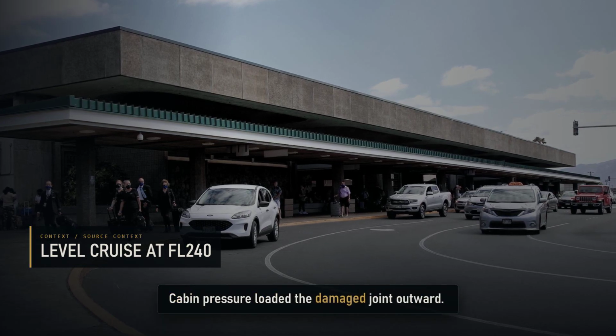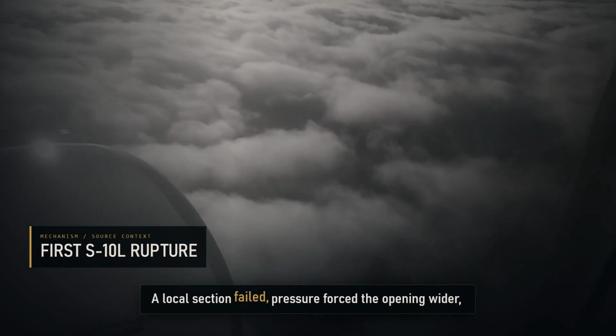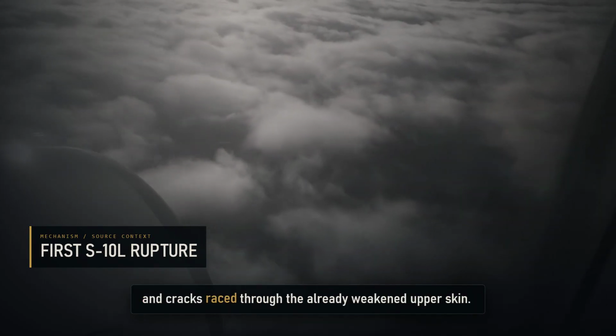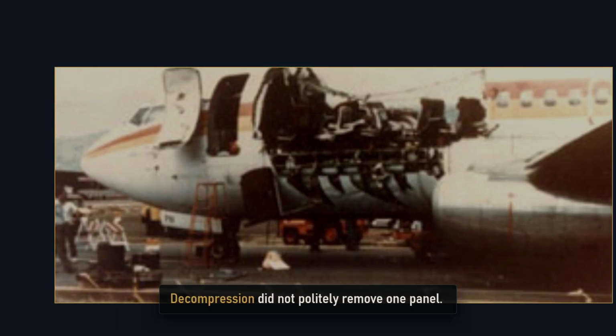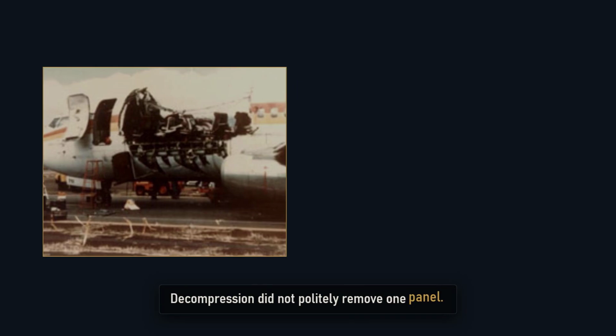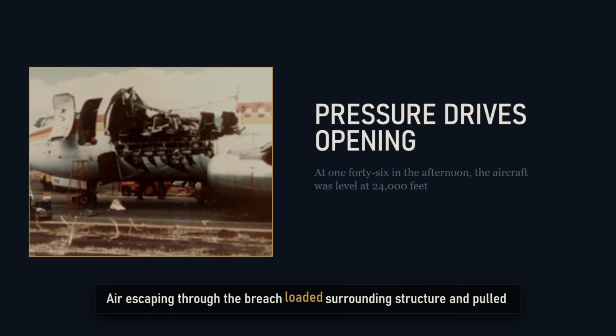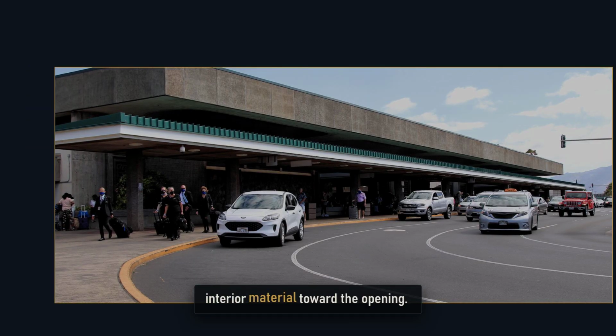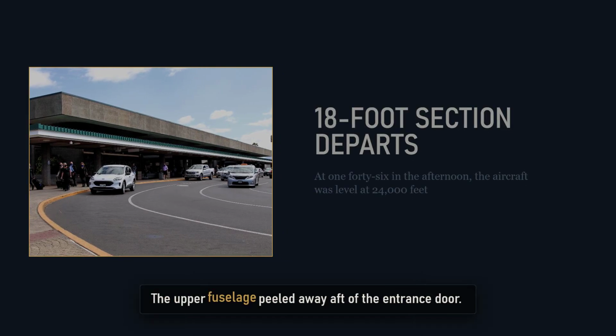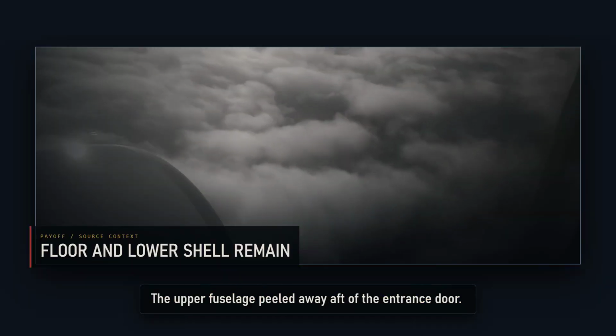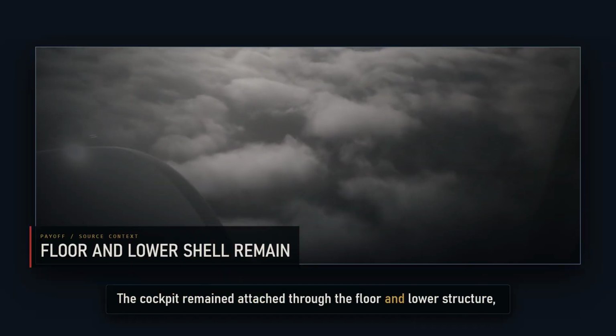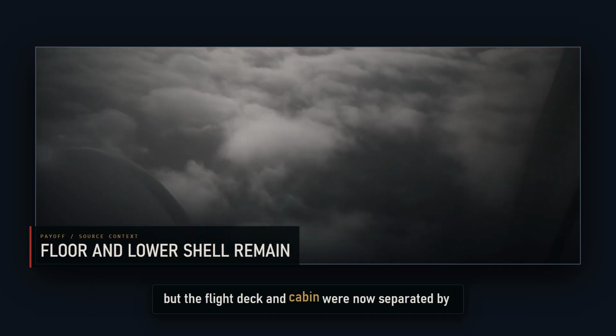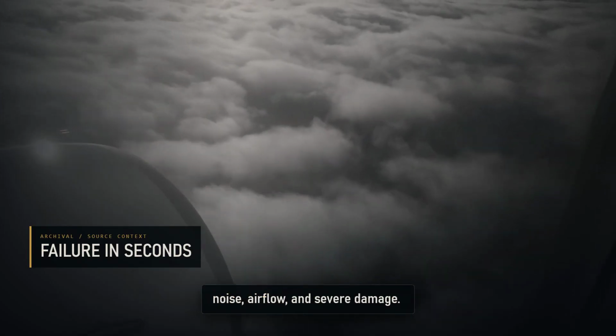Cabin pressure loaded the damaged joint outward. A local section failed, pressure forced the opening wider, and cracks raced through the already weakened upper skin. Decompression did not politely remove one panel. Air escaping through the breach loaded surrounding structure and pulled interior material toward the opening. The upper fuselage peeled away aft of the entrance door. The cockpit remained attached through the floor and lower structure, but the flight deck and cabin were now separated by noise, airflow, and severe damage.